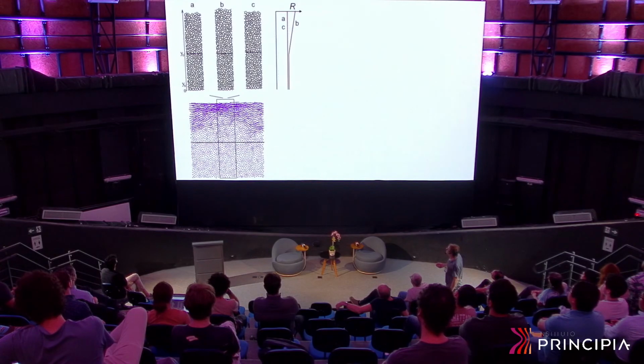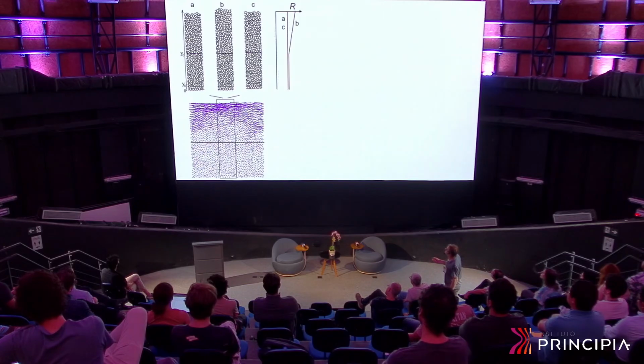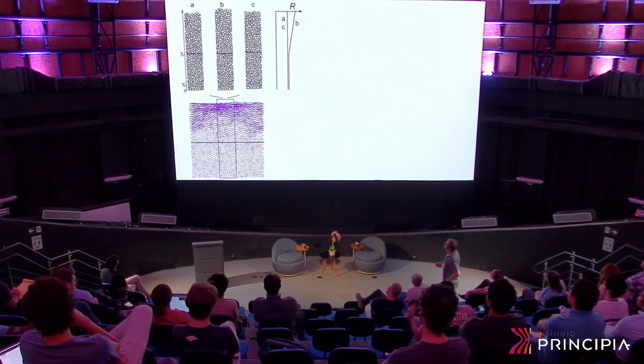Here the dots indicate the original configuration of the particles, and the final configuration at this plot C are given by the tips of the segments that start on each particle. So you see that in a cycle of increasing and decreasing of the radius, the particles at the surface have moved the most to the right, and as we go deep into the system, they move less and less, and essentially where the radius didn't change, the particles remain in the same original position.